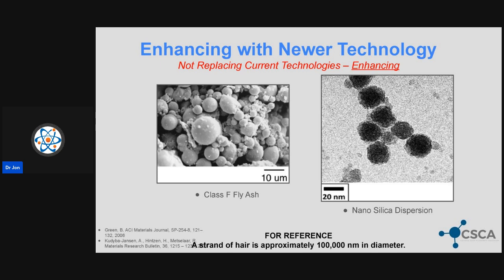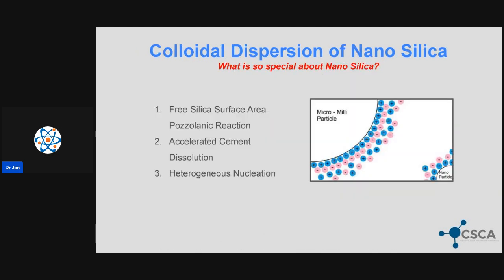And because it's smaller, we're going to have some different positive benefits we can take advantage of, not only for other value-added performance like abrasion resistance and permeability, but also alkali silica reactivity. Now, what's so special about nano silica? First of all, we have this free silica surface area for pozzolanic reaction. I often refer to the team Land and Stephan, who wrote a paper back in 2012 that talks about this instantaneous pozzolanic reaction that they refer to as the calcium silicate hydrate seeding effect.